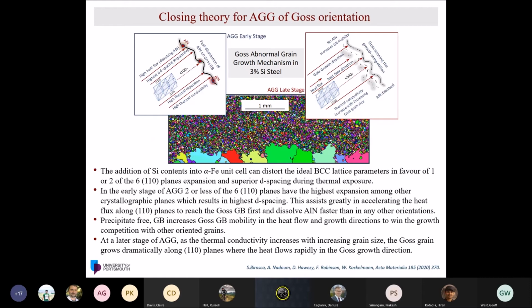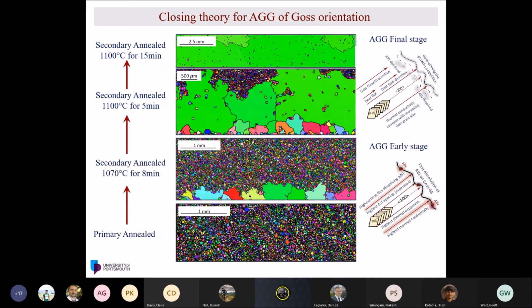Okay, so next slide, I'm showing the in situ results from the primary anneal, and we monitored all the secondary anneal after 1100, and this is what gets us to this conclusion: how the heat flux is helping the 110 plane to reach its grain boundaries to dissolve the precipitates, and then this clear boundary of Goss is already there. So then the high mobility grain boundary will play its role at a later stage of the abnormal grain growth to expand and consume the rest of the grains in the sheet.